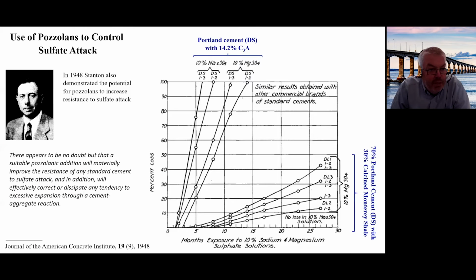Stanton was a pretty smart guy. Eight years later, he published work to show that pozzolans were also effective in controlling sulfate attack. And we look at this graph here. This is from his published work in 1948, published in the ACI journal. And you can see in blue there the line showing a very rapid deterioration of mortars containing straight Portland cement with a very high C3A content, whereas the mortars with 30% calcined shale perform much better, with no deterioration occurring in sodium sulfate and a reduced rate of deterioration in magnesium sulfate.